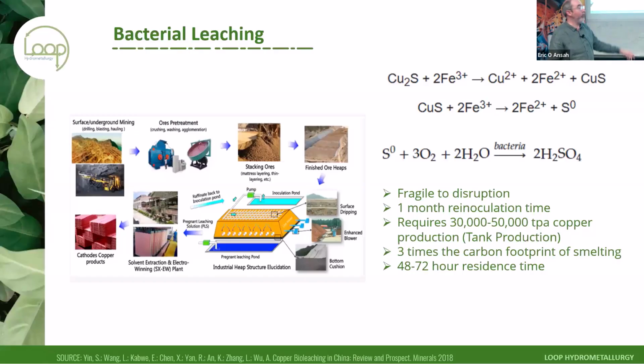I don't think bacterial is a good choice for a lot of areas where power supply is anything less than completely stable. In terms of comparative scale, these days you pretty much would not build a smelter at less than 250,000 tonnes per annum of copper output. You pretty much wouldn't build a pressure oxidation facility smaller than 100,000 tonnes per annum, and probably 150. Your minimum for a bacterial is 30 to 50,000 tonnes per annum.